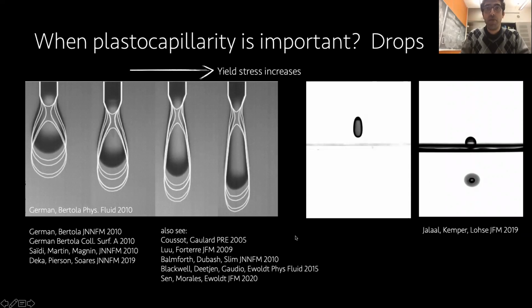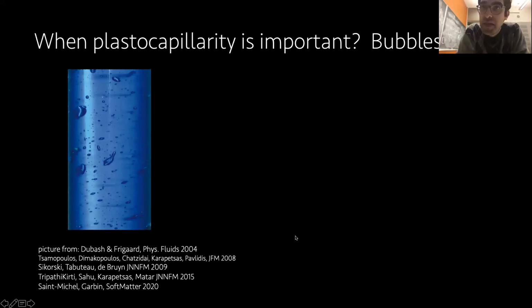But another place where viscoplasticity or plastocapillarity can be important is bubbles. The picture I'm showing on the left is from the paper of Dubash and Frigaard. What they're showing there is the static shape of bubbles. If you put bubbles in Newtonian fluids, surface tension wants to make them spherical. But the yield stress of a viscoplastic fluid resists this, so you can get arbitrary shapes like those shown here. There is a series of nice works from the group of John Tsamopoulos on simulations of rising bubbles inside yield stress materials. John De Bruyn also has done some work on that.